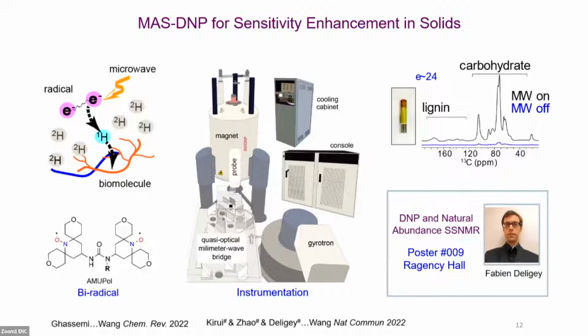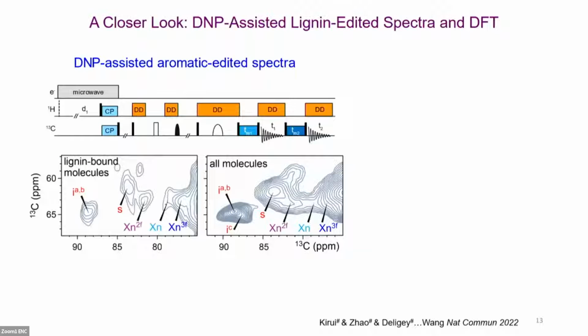Here we use the biradical AMUPol. The gyrotron gives the microwave to irradiate the AMUPol, and we can transfer the polarization from the electron to the proton and then to the carbon in the plant cell walls. Here, we got a 24-fold sensitivity enhancement. With this big enhancement, we can collect the DNP-assisted aromatic-edited spectra.